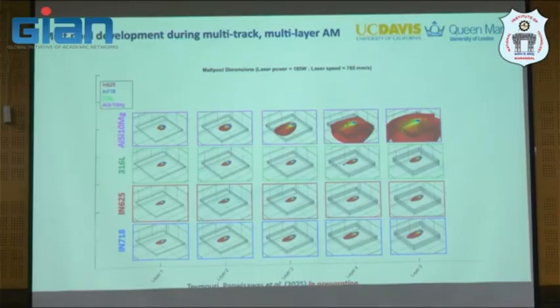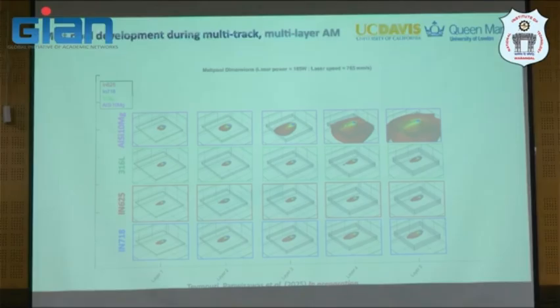And one additional aspect, we can do multi-track, multi-layer AM. That means we can deposit whatever you like, but now layer 1, layer 2, layer 3, layer 4, and layer 5 here. And then you will see that the melt pool is not actually at what we call steady state. In welding, probably you can say steady state, but here the heat beneath actually contributes to the size of the melt pool for the next layer and the next layer whatsoever. So there is no such thing as steady state in additive if we do not control it very well. So this is one message from this slide.